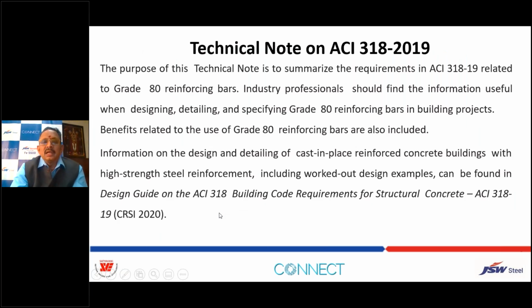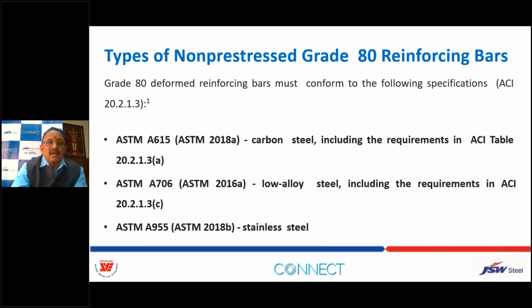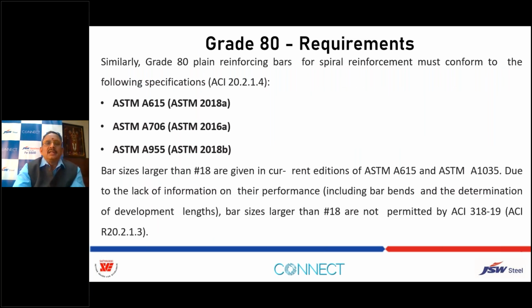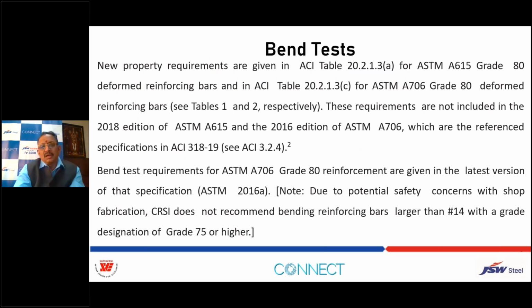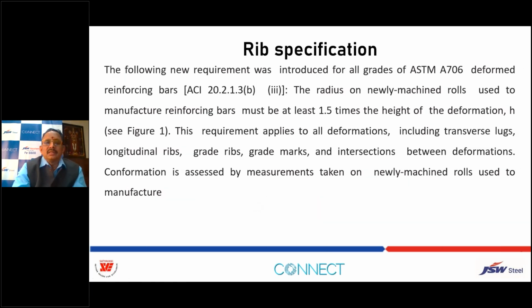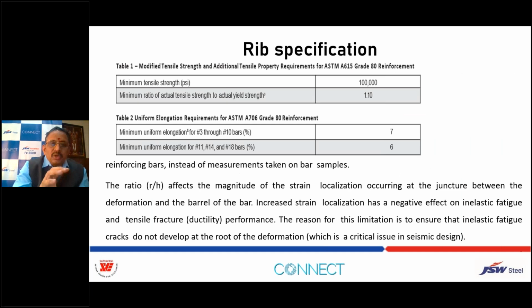So these are the ACI provisions, which we can adopt using ASTM for testing methods, and then we can use the bend tests also for these higher grades. We can conduct these bend tests as per these provisions. It will help us because IS 456 or IS 1786, we have up to 600 actually, but in IS 456 we have a limitation up to 500. So until it is revised, we can take support of this ACI, and minimum percentage elongation and minimum ratio of actual tensile strength to minimum tensile strength, for 100,000 we can use 1.1.